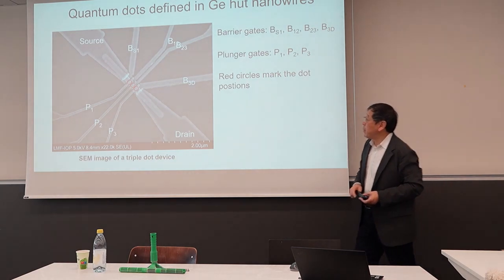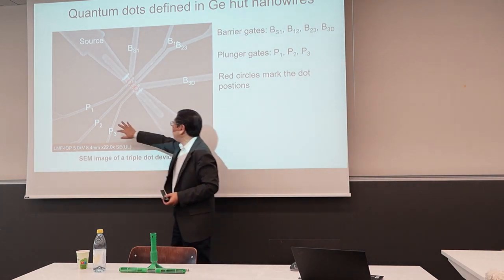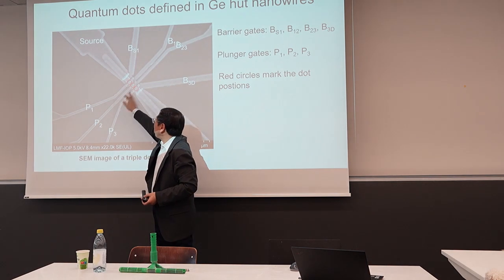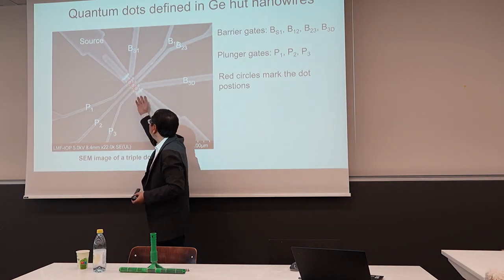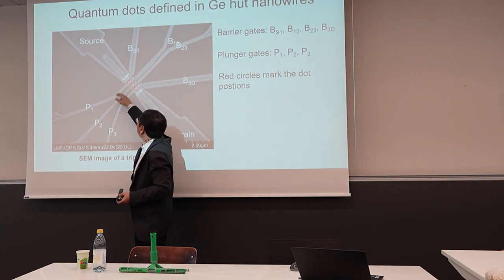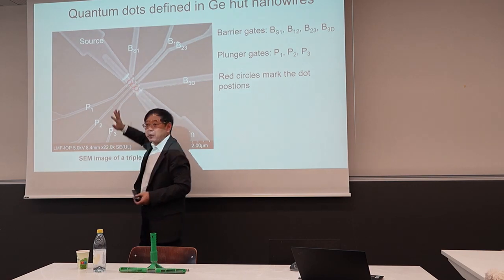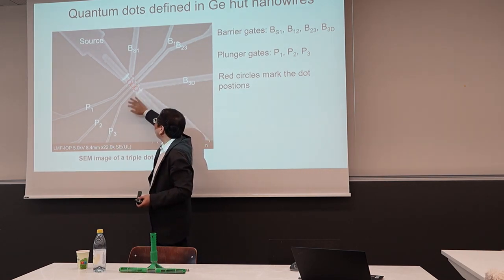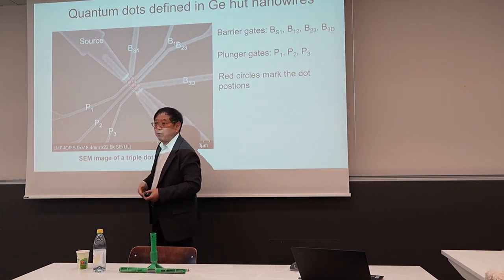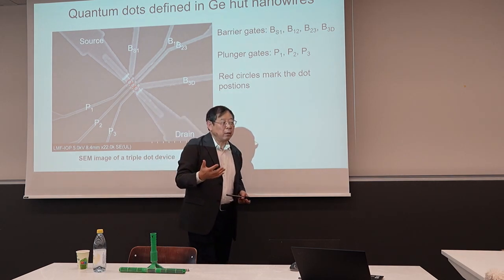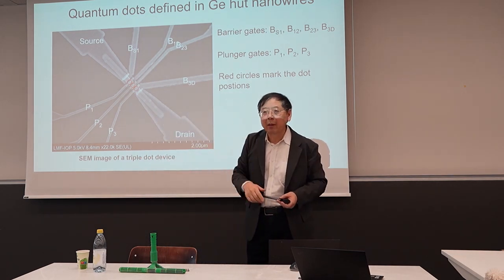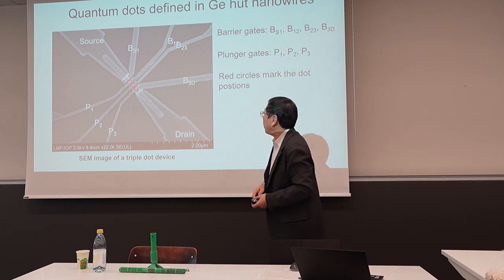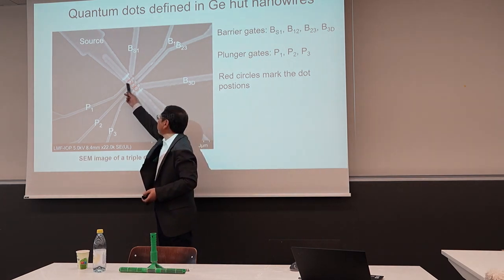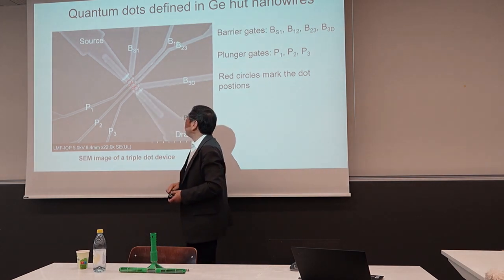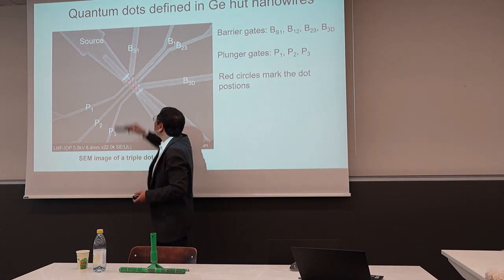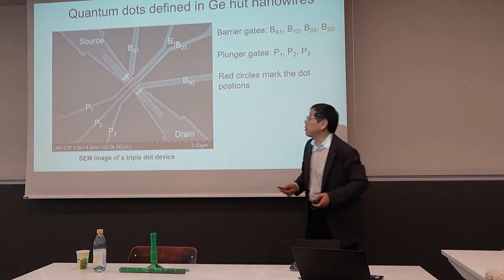Then we can make, again using our gate technology for this sample, contacts with, in this case, aluminum, and we use some dielectric and two layers of finger gate. One layer defines the barrier gate, another layer is the plunger gate. So in this case, this triple dot, we can really manipulate with these two plunger gates. So that is what we can do.